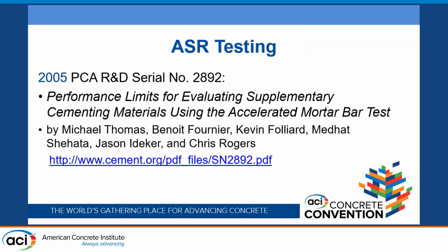Of course, you're going to hear a lot on ASR testing throughout today. One of the works that he really pulled together a lot of information, and this is when this test became extremely popular, was the performance limits for evaluating SCMs when using the accelerated mortar bar test. This was originally developed for the purpose of identifying ASR aggregates, but it's been widely used for SCMs, and a modified version of AMBT was conducted and turned into ASTM C1567 at the time of this report. It was a very important report to us, especially for the findings.